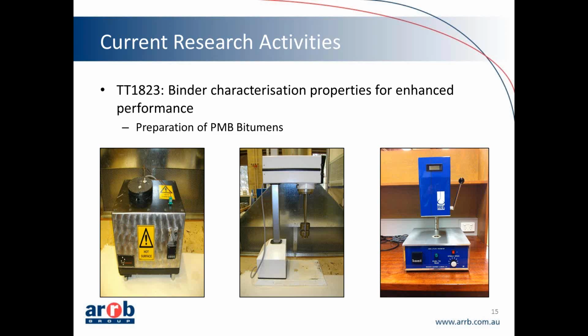Great. Well, I do have a question for you, Shannon. How much bitumen can be blended at any one time? Okay, so in the 1 litre heating block, we can blend up to around 800 grams effectively. For the 4 litre, we can blend around 3.8 litres of bitumen. Because we needed between 16 and 20 odd kilos of bitumen, we had to do quite a few blends, but we had a splitting process where we made sure that the binder was completely homogenised and tested for critical properties throughout the process.